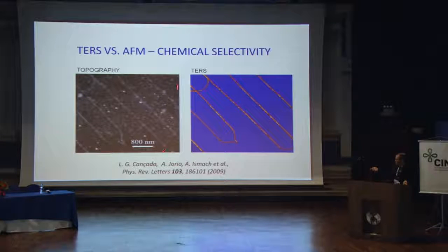Here is a regular AFM image of a nanotube serpentine, and here is the corresponding Raman image. And the difference you see is, in microscopy, you only see if there is something there or not. So there is something here, but there is also something here. And I know this is a nanotube because I know I put it there. But otherwise, you would have no information. But when you do it with spectroscopy, you also have the spectroscopy information. So at the end, the information you have is much richer than what you can do with microscopy.